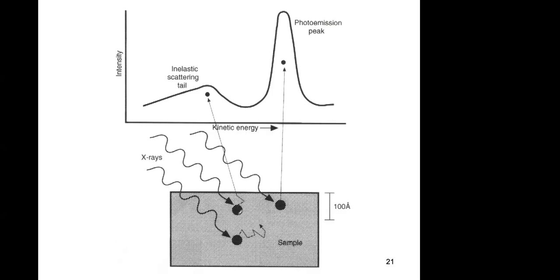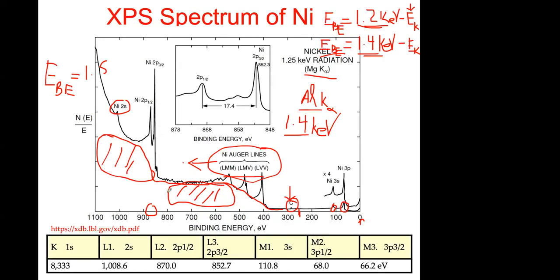But if they are close to the surface, maybe they have collisions and they lose energy. If they don't have collisions, you're going to exactly determine their kinetic energy. But the ones that have collisions make up the background. Since the collisions are different for all the electrons, you don't see a peak. You basically see a background. This is like an ocean of electrons with different kinetic energies because of the collisions, you see?